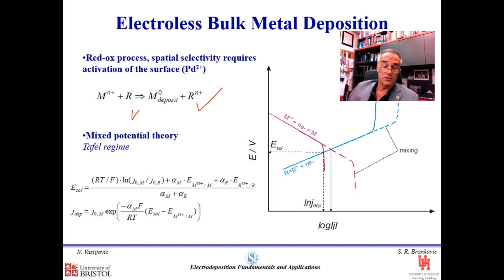So in order to understand whether the electroless deposition is going to work and whether we are going to get what we want, we need to understand where the solution potential will be. And in order to have a good idea about solution potential, we have to do certain measurements. However, we can do also some predictive work where we can actually do electrochemical characterization of our reducing agent and run the sweep voltammetry and get current density over potential characteristics, and also we can electrodeposit our metal and get also characteristic features of this voltammetry.